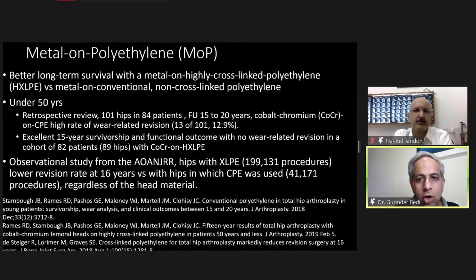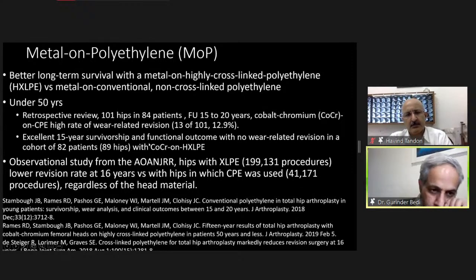What about metal on poly, which is the conventional one, which is much, much more economical, which most of us will be using? The answer is on a highly crosslinked poly, much better result compared to a simple conventional polyethylene. So when you compare the results of conventional versus this, what you see is excellent outcomes with a crosslinked poly. So if you're going to use a metal, do try to use a highly crosslinked poly, which has been shown in pretty much every registry that you talk about.